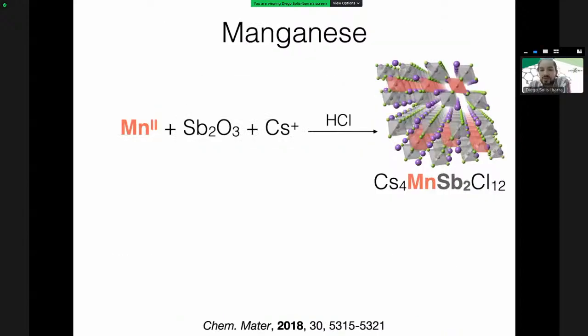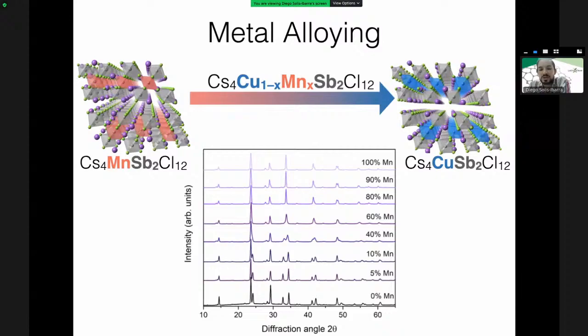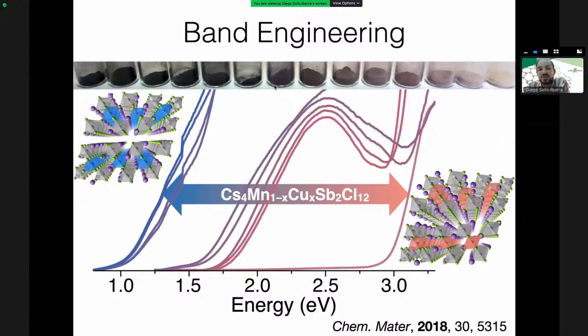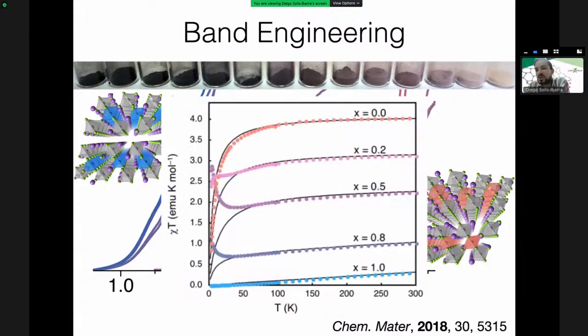So Brenda was quick to prove that you could also put manganese instead of copper, and when incorporating manganese, you also change the properties of these materials. Also, very importantly, you can modulate the amount of manganese. You can do solid solutions and progressively introduce different amounts of manganese in these materials. And what this results in is a modulation of the bandgap and the properties of these materials. So you can see here that the manganese-only material has this pale pink color, the traditional color of manganese. And as you go to the copper-only material, you get the bandgap of 1 electron volt, and depending on the concentration, you get this plethora of different properties or different bandgaps. Of course, when you're talking about manganese and copper, you are also changing the magnetic behavior of this material, which is really interesting to explore.